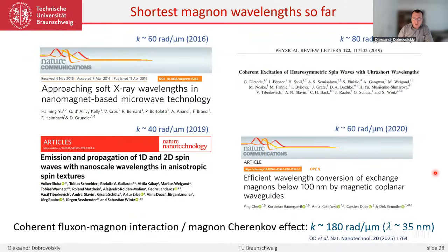In terms of the wavelengths, it is interesting to compare that during many years, so 5 years, it has taken people to just increase the K vectors by a factor of 2 extensively by using some grating coupler approaches or reducing the size of microwave antennas. But now, because of this paradigm shift, just transferring this towards Fluxon-Magnon interaction, we have achieved K vectors of the order of 180, so basically by a factor of 2.5, beating the previous records and now having at our disposal wavelengths of the order of 35 nanometers for spin waves.